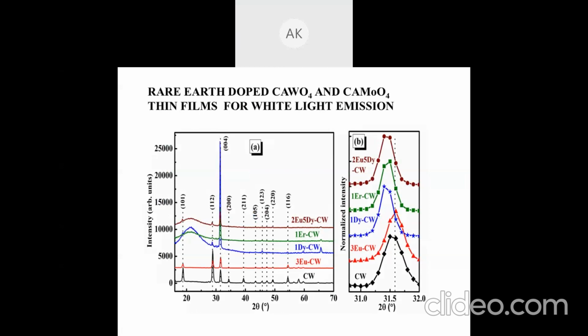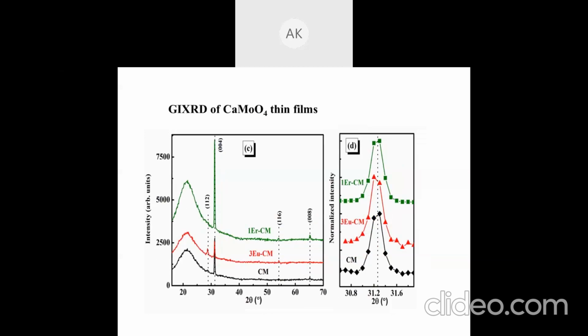And during deposition, you heat the substrates to a temperature of about 650 degrees Celsius in order to get the crystalline phase. So we get films which are again tetragonal phase. And in the thin film form of the calcium tungstates, these are single phase materials, and the dysprosium ions are actually doping. They are entering the crystal structure of calcium tungstate and calcium molybdate. And the films are also highly textured. That is usually a feature that thin film materials are more strongly textured. That means there is a growth of the thin film along some particular orientation or direction.